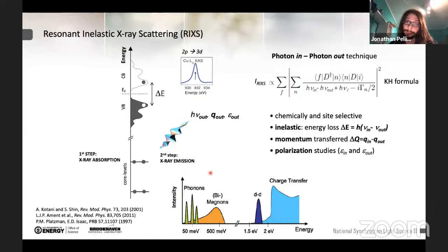If we were to look from a bit more theoretical perspective, if we want to describe the RIXS process, we need the Kramers-Heisenberg formula, which involves a second order process where we have to involve two dipole operators, and we have the intermediate state here, the final state here, and if we want to calculate the RIXS intensity, we have to sum over all the possible intermediate states. Importantly, RIXS is chemical and site selective because we can tune the incident energy to an absorption edge and select the site, so which atom we decide to investigate, and also which orbital, depending on the X-ray absorption profile.